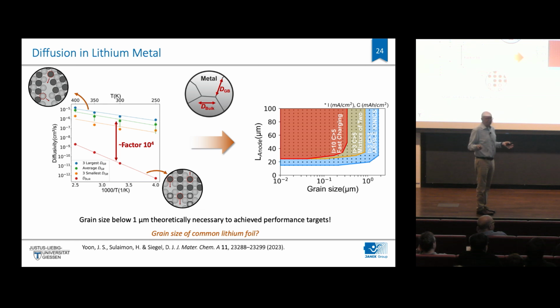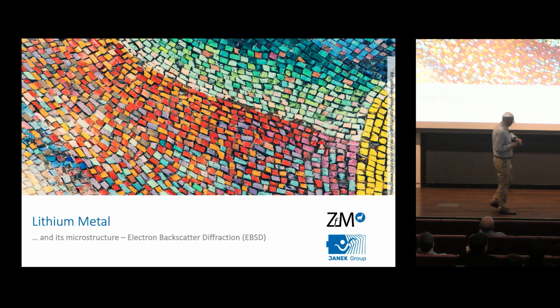And then the question is, can we get that? Can we get lithium metal with a grain size below 1 micron? And the answer is very difficult, and at the end it doesn't make sense, because the true and the best electrode or concept we will see is, of course, something where you don't bring in any lithium originally into your cell. Okay, and this is then the story of particularly 2 brave PhD students in my lab. Nobody really had ever looked into the microstructure, into the cross-section of an alkaline metal, because they are so sensitive.